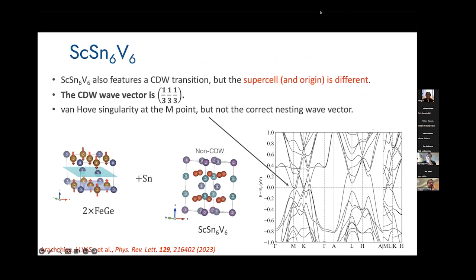But before this, I wanted to start with the system that basically attracted our attention. And this was ScV6Sn6, which doesn't have any flat bands at the Fermi level. It doesn't have magnetism. Well, there's a new paper that claims some magnetic fluctuations, but so far, as far as I know, no magnetism. And the Fermi level is at, or close to, a Van Hove singularity. It has a CDW state, and the CDW vector is 1/3, 1/3, 1/3. The Van Hove singularity is not at the CDW vector.